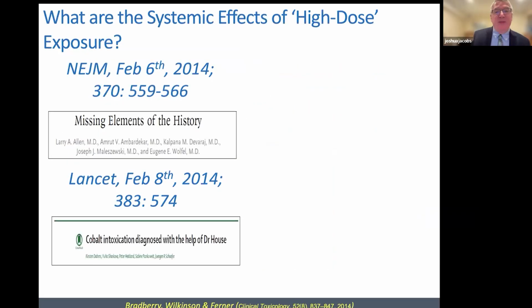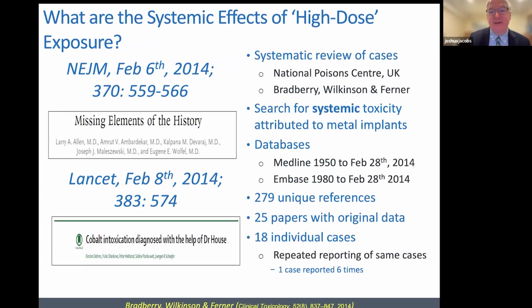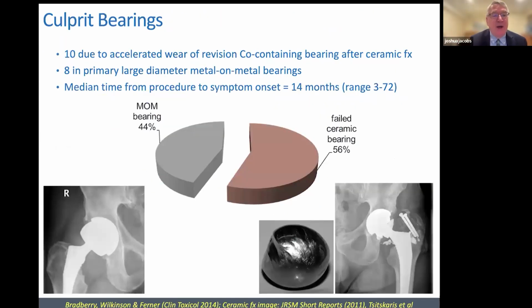Now, there are some cases where metal levels can get quite high and lead to very dramatic toxic effects. If we search the literature for this, we found out that they're very rare, but they are very severe. We see them, for example, not only with metal on metal bearings, but also in a situation where you have a failed ceramic bearing. So if you have a fracture of a ceramic, at the time of revision, you can remove a lot of the ceramic debris, but some of the ceramic debris, essentially glass, stays behind.